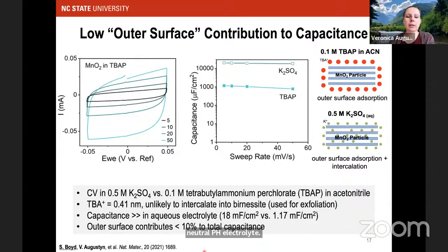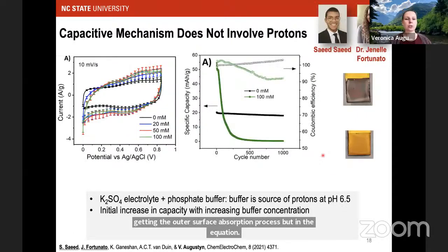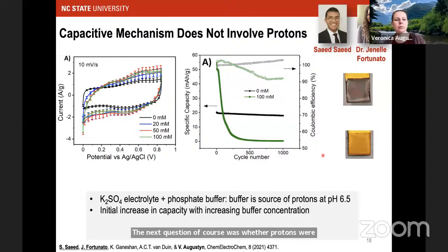It's about 10% of the total capacitance. And what that told us is that in these bulky cation electrolytes, there's no protons, no small cations present. We're just getting the outer surface adsorption process, but in the aqueous electrolyte, we must have insertion processes taking place as well. The next question, of course, was whether protons were also involved.